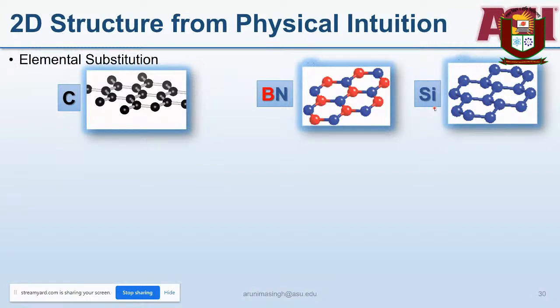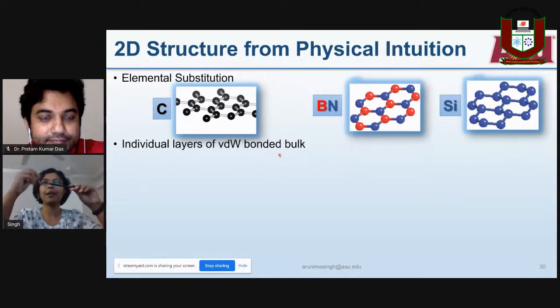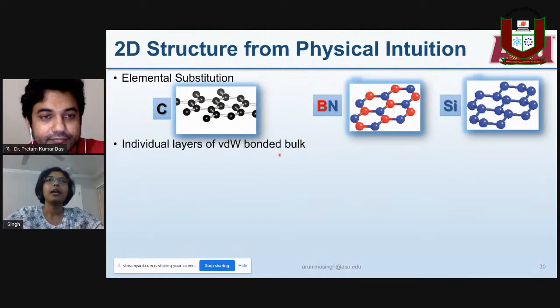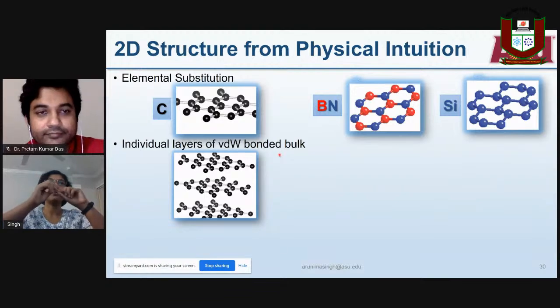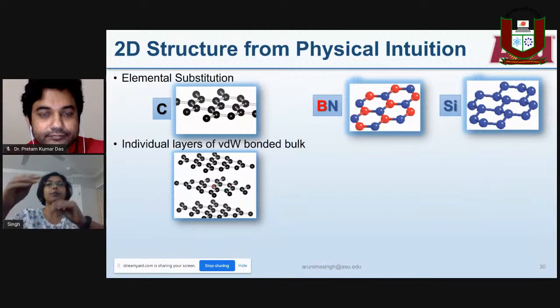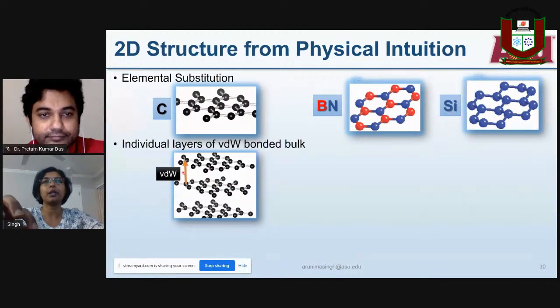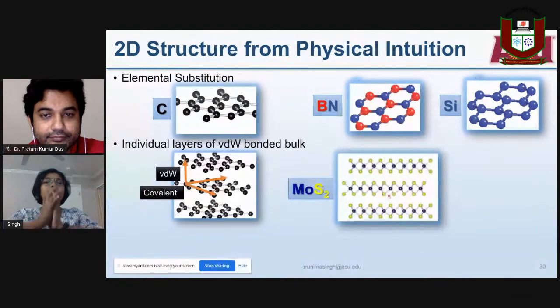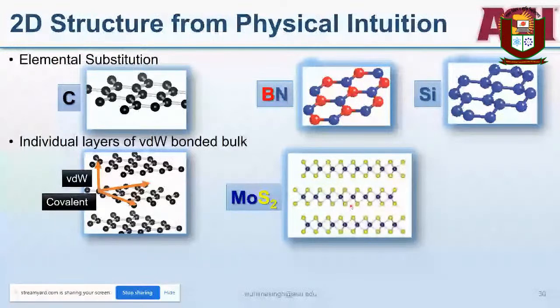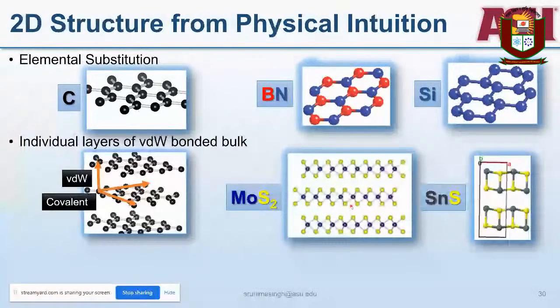This led to the discovery of many 2D materials, but the other approach was looking at individual layers of van der Waals bonded materials. How was graphene actually discovered? If you look at a pencil and use Scotch tape to peel off the graphite from your pencil, and if you keep doing that repeatedly with the Scotch tape, you're going to get a graphene flake at some point. And what is happening is, every time you do that, these individual layers of graphene are breaking. The van der Waals bond, which is very weak, is breaking, and the covalent bond, which is 10 times stronger than the van der Waals bond, remains. So your graphene sheet remains intact. And using that idea, people thought if you look at other van der Waals bonded bulk materials, we can find other 2D forms which could be stable, such as MoS2, tin sulfide.